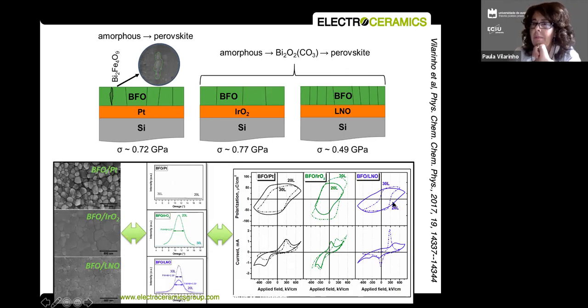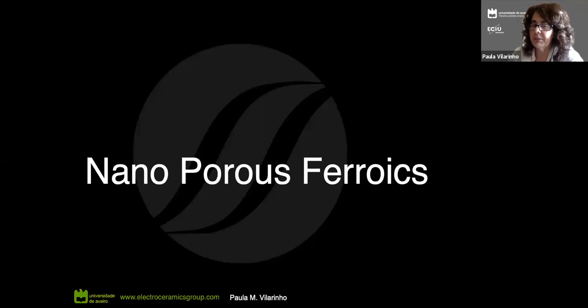It looks like our oxide films like to talk with oxides. So these are two oxides and we expect a better response. And that's indeed what is happening. Even the phase formation of the film on top of an oxide is much faster than when I have a metal. So again, the message is that when we use the buffer layer, we really engineer the properties of the materials.